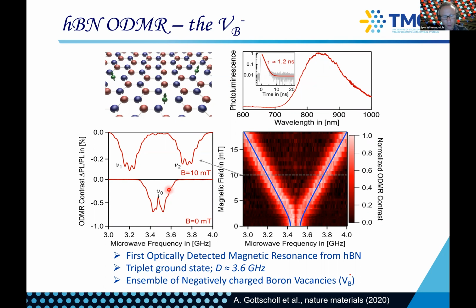And what was remarkable is that when you scan your microwave around it, you would see a very pronounced peak at about 3.5 gigahertz. And as you apply magnetic field, here the peaks would split. So this is a perfect spin one system. And it was the first ODMR signature at room temperature from hBN. This is still an ensemble.